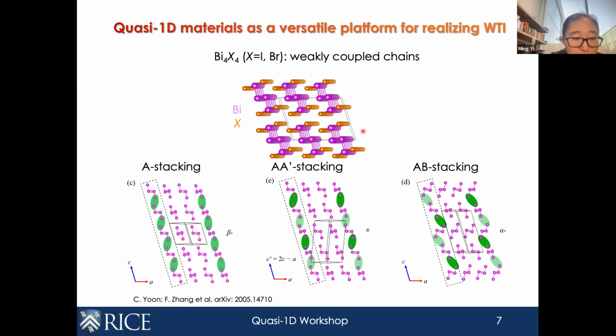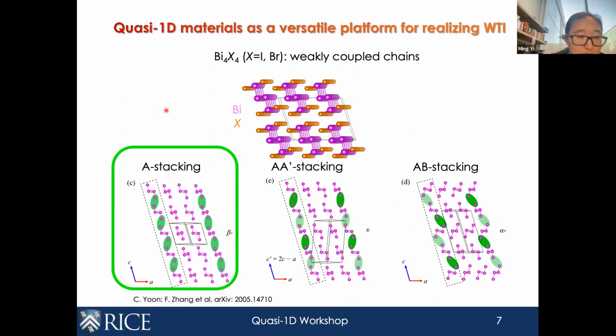And then we can also have a dimerization realized in two types of stacking: AA' stacking, where there's some sort of small shift, so the basic unit cell consists of two blocks. Or you can have what's called AB stacking, where every other layer is flipped 180 degrees. And as Fan also demonstrated, these two would give you different types of inversion centers. I'm going to come back and discuss this later. But let me first demonstrate from photoemission what we find with the simplest stacking, which is just the pure single block A stacking phase of the bismuth halides.